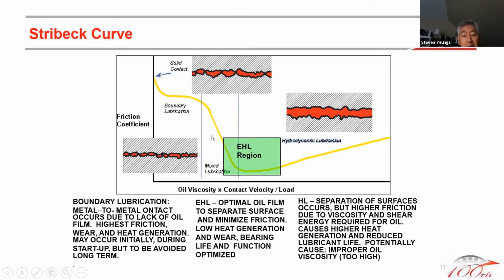At that time, the friction drops, and at some point it goes back up again as the oil film becomes too thick, or increasingly thicker. From the bearing perspective, we try to aim at this green box, which is referred to as elastohydrodynamic lubrication conditions. There we can optimize the oil film, have minimum heat generation, but have enough oil film to prevent metal-to-metal contact and separate the surfaces, while at the same time generating the lowest heat possible. As I mentioned earlier, an oil film getting thicker and thicker might not be a good thing in some applications. The thicker the oil film, the more unnecessary shear energy or shear stress you generate within the lubricant itself. It's like running inside a swimming pool.